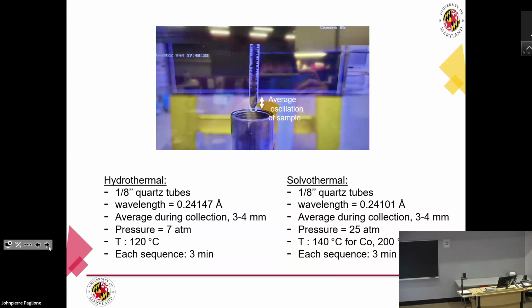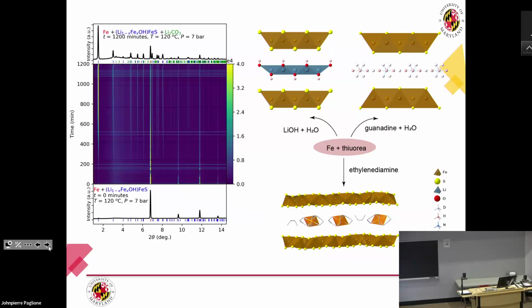And we take thousands of powder patterns. And this is an example of the pattern as a function of time. So this is from 0 to 1200 minutes. Here we start out with all iron metal, and then we get to our product that we're after, with some byproducts like lithium carbonates. There's always some CO2 in water as well, right? It's pretty soluble in water, so you'll generate some carbonate sometimes. So if you're really worried about things like that, that may interfere with the crystal growth, you can figure out maybe a way to decarbonize or de-CO2 your water.